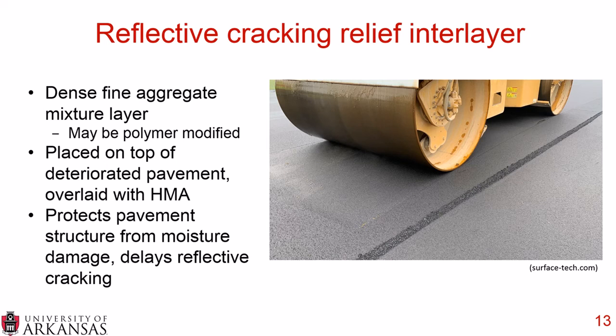Now, when we say fine aggregate mixture, we usually mean greater than 98% is passing the 3/8 sieve, which is the 9.5 millimeter sieve. So almost a sand mixture, but a very fine mixture.